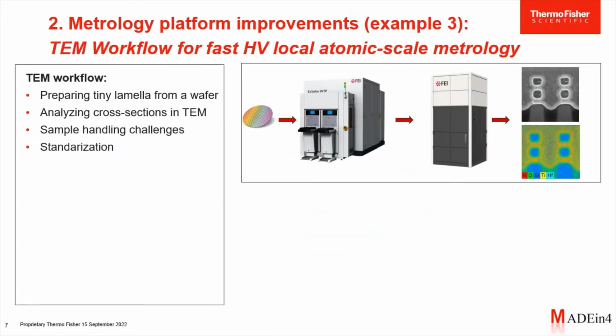As a final example, I would want to spend a bit more time on the work we've done in Thermo Fisher around the TEM workflow. The TEM workflow is ideal to obtain local atomic scale information. And what we've tried to develop is to do this also at high volumes. The TEM metrology workflow starts with a wafer and then uses a dual beam device to cut very tiny TEM lamella out of that wafer. And tiny, you have to think about microns. Those lamella are then transported into an electron microscope, which then yields all types of different information, including dimensional metrology as well as compositional analysis.